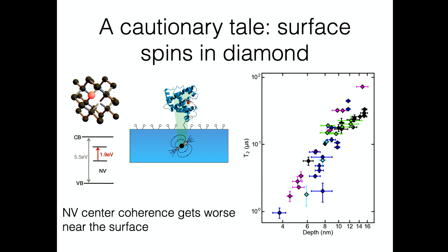So let me just take one step back and give you a cautionary tale from Diamond World, because I think this really informed my particular scientific approach to this problem. So sorry to give you like a second introduction in under 3 minutes, but about 2/3 of my group is actually working on this little color center in diamond. So if I take a diamond, punch out 2 carbon atoms, and stick in a nitrogen, I get something called a nitrogen vacancy center. This gives me a very deep electronic defect that even has excited states, electronic orbital excited states that are also deep defects. So I can do things like put in photons, take out photons without really thinking about the surrounding diamond lattice.